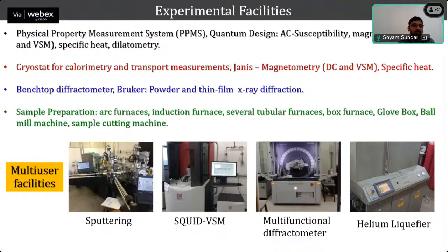We have another cryostat for calorimetry and the transport measurement from Janis. And we have a benchtop diffractometer for the X-ray diffraction on powder and thin film samples. And we have several furnaces for the sample preparation. For example, we have the arc furnaces, induction furnace, several tubular furnaces, box furnace, glove box, ball milling machine, and sample cutting machine, etc.